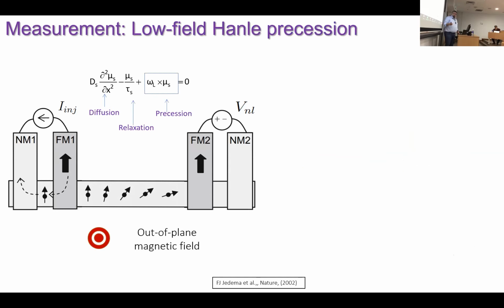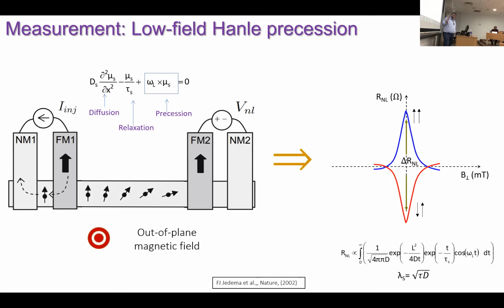The second way is you have again the same non-local geometry, but this time you apply an out of plane magnetic field. The spins which are already in your channel material start to precess along this magnetic field, and you get this oscillating type signal, which we call the Hanle spin precession curve. From there, by doing the fitting, you can directly get information about the spin relaxation time and the spin diffusion constant. And from there, you can again get information about the spin relaxation length.